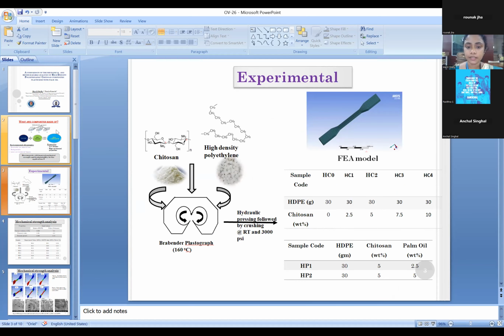This is a schematic representation of the experiment which I have done. Initially, I have melted high-density polyethylene at 160 degrees Celsius, and to the melted mix, I have added varying concentrations of chitosan. The compatibility of HDPE and chitosan was improved by using dicumyl peroxide as free radical initiator and maleic anhydride as the compatibilizer. A set of HDPE chitosan composites were prepared, and the system was optimized with the help